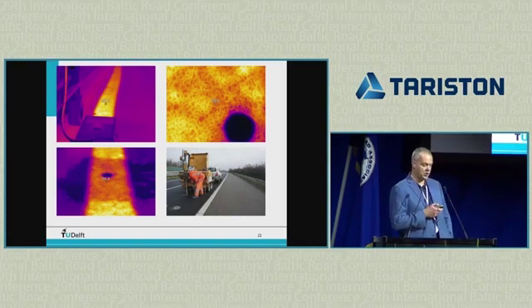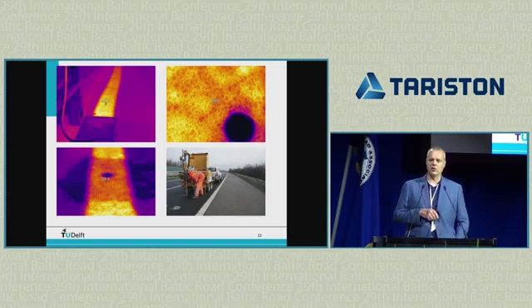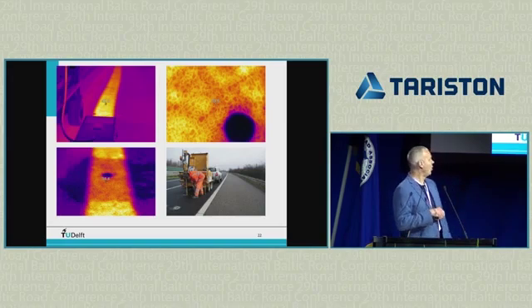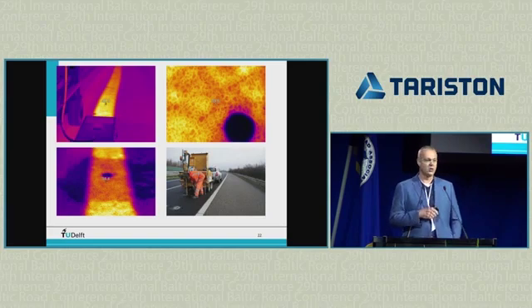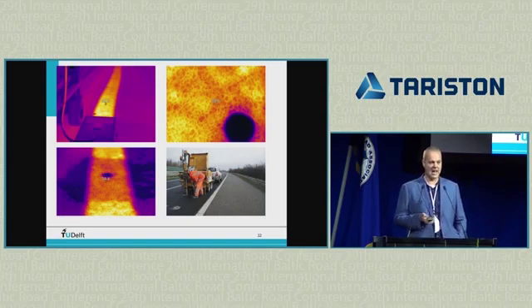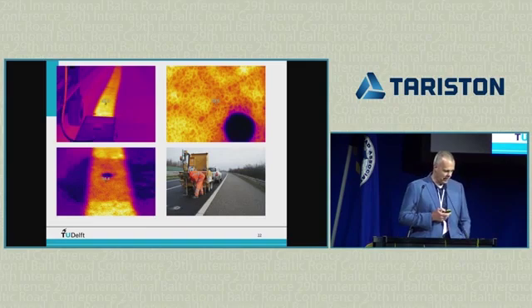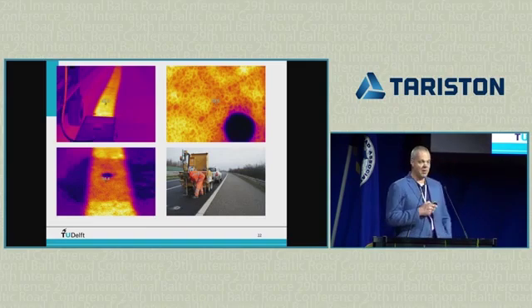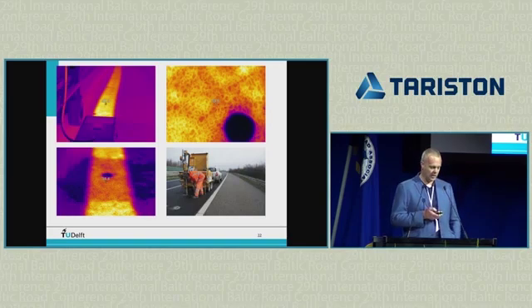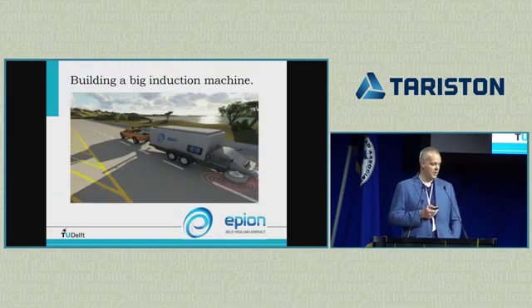So here you see again, we also found a black hole when we were driving over the asphalt. So here you see the black hole. That was actually where we drilled some cores after we made the pavement, and that hole was filled with normal asphalt, without steel fibers. So you see already that you cannot heat up the asphalt when there are no steel fibers, because you heat up the steel and not the asphalt itself. So this was 3 years ago. We went there with our small induction machine, just a prototype, and we are now building with this small company, as I said, a big one that we can drive at a relatively higher speed, because the first one was just walking speed. We want to go somewhat faster with this big induction machine, heat up the road, and then see if that really works.